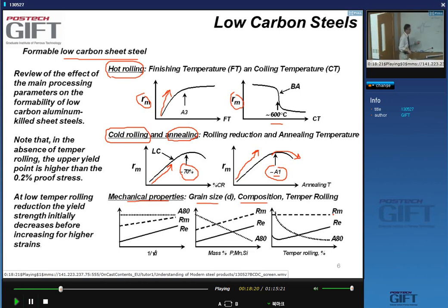What do we see? We see that the UTS doesn't change, right? As a function of the temper rolling, the amount of deformation you give, the UTS stays the same, yes? The yield strength decreases, because the yield point here will be higher than the yield point in this case, and it depends how much deformation we give. So it has this shape, the yield stress, and there is a minimum. And what happens to the elongation? Well, the elongation goes down, right?